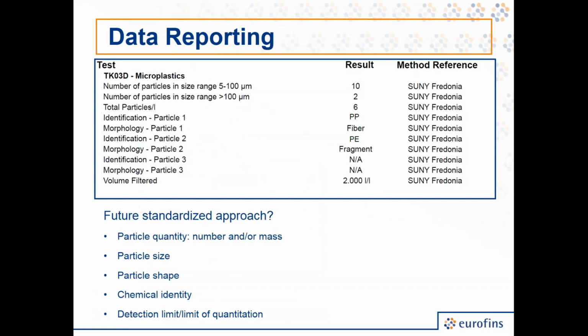Now, in general, we report data in this format. So this is an actual snippet of a report. So what you'll see in a typical report are size ranges in 2 different categories, and with a number of particles reported in each category. And note here that in this case, we tested a 2-liter volume of water to generate as one sample. In addition, for certain particles, it depends on how many a client wants to characterize, we will determine what is the material. So what is the chemical identity, in this case polypropylene, and it happens to be a fiber.